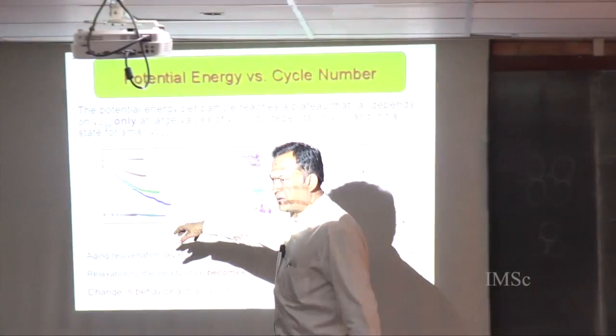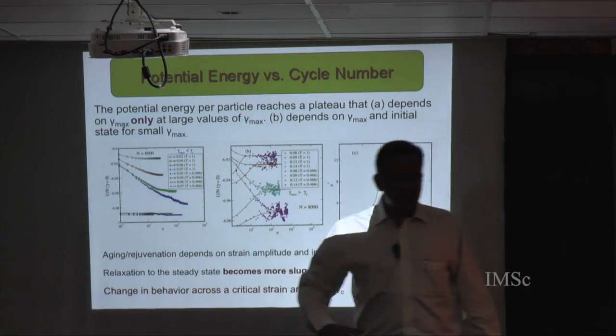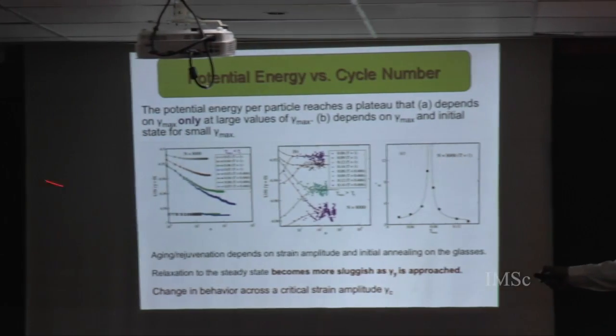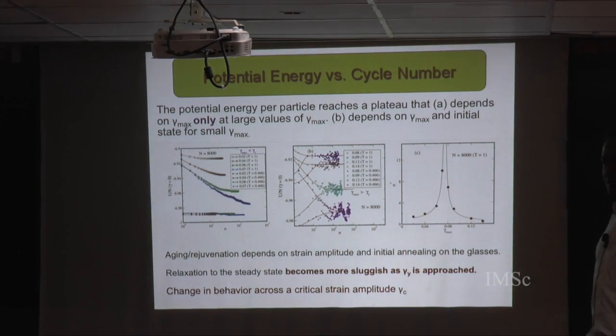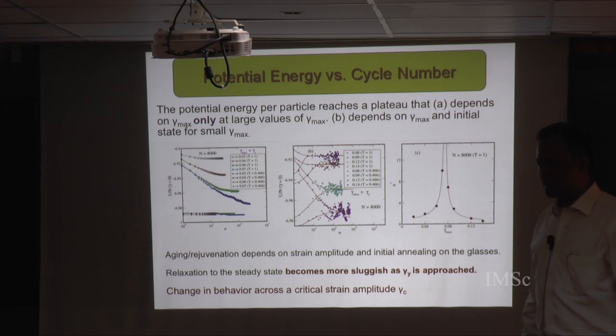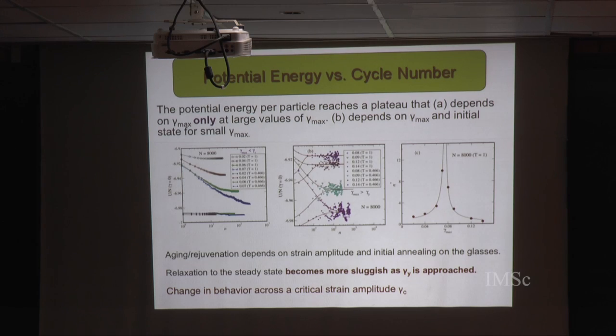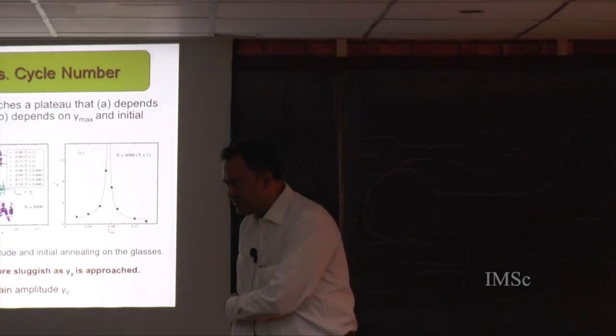So this is the behavior you see, but there is annealing of the system with cycles, and it is a slow process with a diverging length time scale as you approach the threshold. So you could call it aging. And besides the fluctuation of the energy as a function of, there are a lot of similarities with tapped granular materials, in which you reach steady state, and there you can study the fluctuation of the energy in the steady state, and do all the thermodynamic formalism.